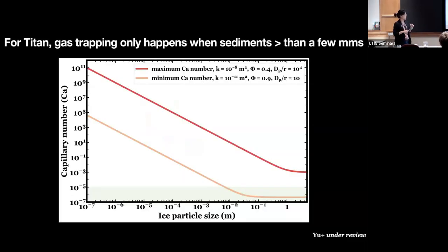So the first thing we did is calculate the capillary number, which dictates whether gas trapping would happen. Basically, when the capillary number is less than 10 to the minus 5, we think it might lead to gas trapping. And what we found is, given all the possible Titan parameters, you have to have pretty big sediment to make gas trapping happen, but not that big, just a few millimeters in size.